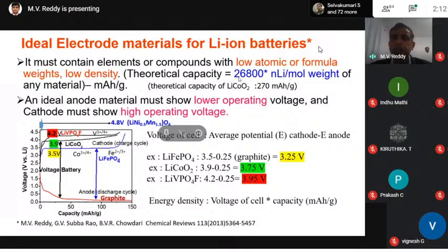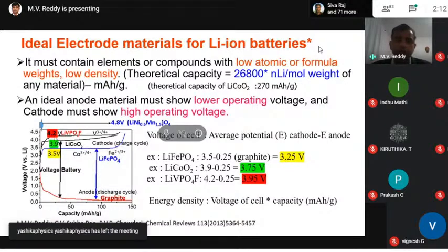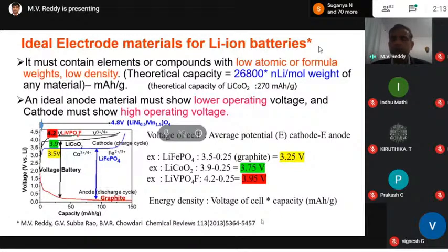Theoretical capacity is calculated using the well-known formula. The anode should have a lower discharge potential, and the cathode should have a higher charge potential. I told you before, the difference between the average potentials, cathode minus anode, gives the working voltage of the cell, and multiplied by capacity it gives the energy density. So always look depending on which plateaus you are looking at.